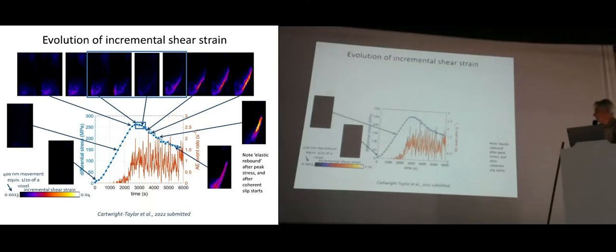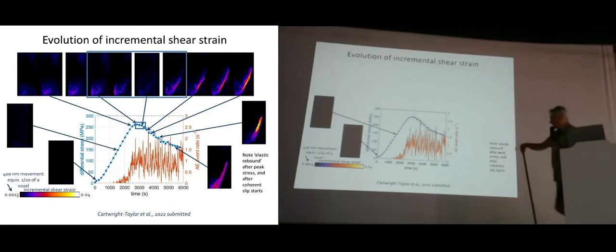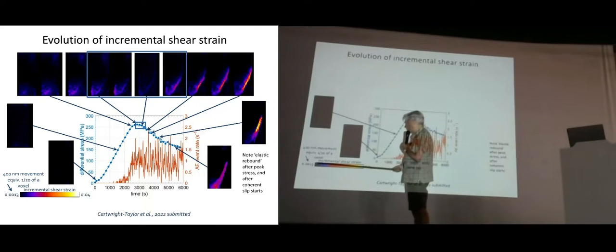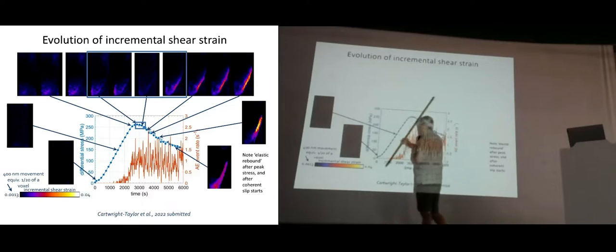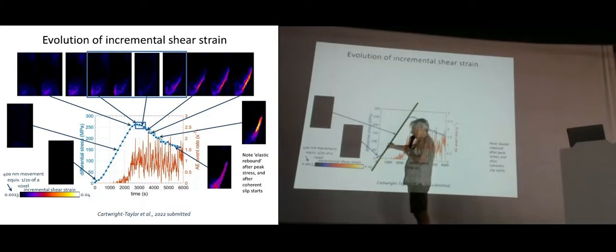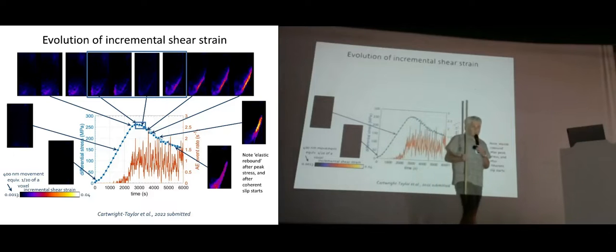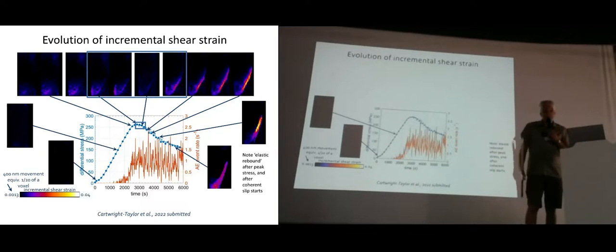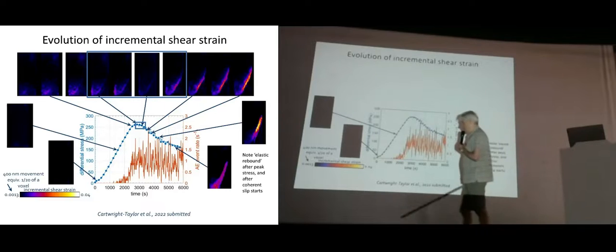And then at peak stress, it's difficult to see, but it's this middle stress, if you like. I don't know if you can make out, you're starting to see some purple, so these cool colors, even when this is linear. So a linear stress-strain relation does not mean there's no damage happening. The damage is happening. It's very small amplitude.